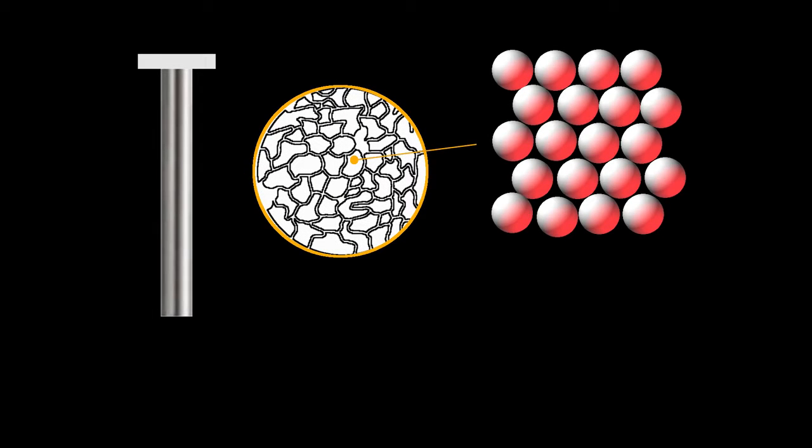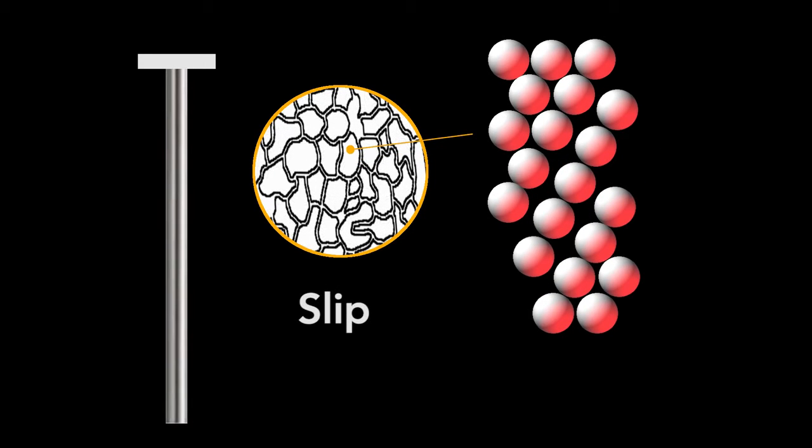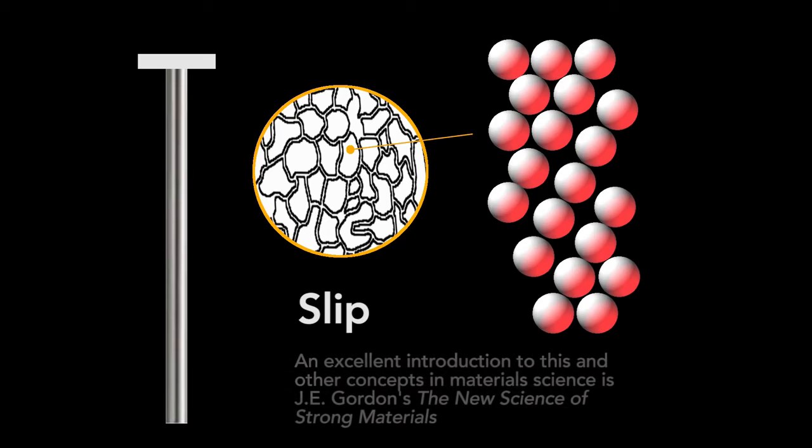In a metal, bonds can reform more easily than in nonmetals, and so the atoms slip, although it's a bit more complicated than implied here, which looks like spherical atoms rolling along each other. It involves defects in the crystal that allow the atoms to move only small amounts. In nitinol, though, generally the atoms don't slip. They accommodate the stresses from bending, stretching, compression, and so on in a different way, which produces the memory effect.